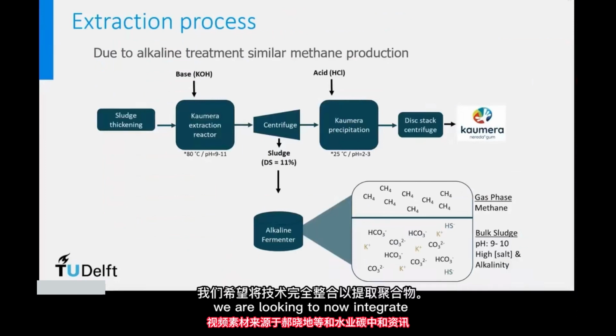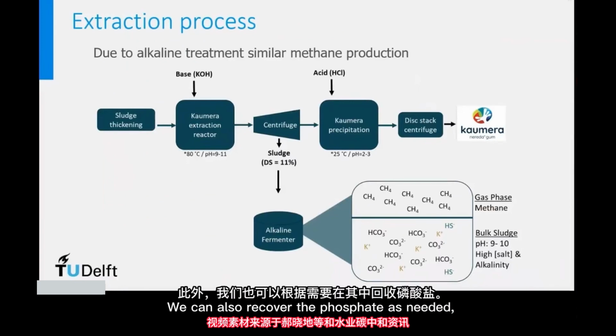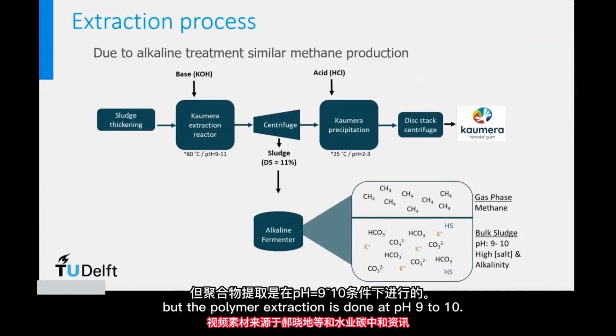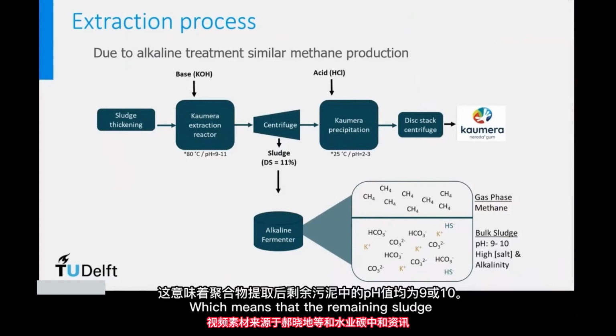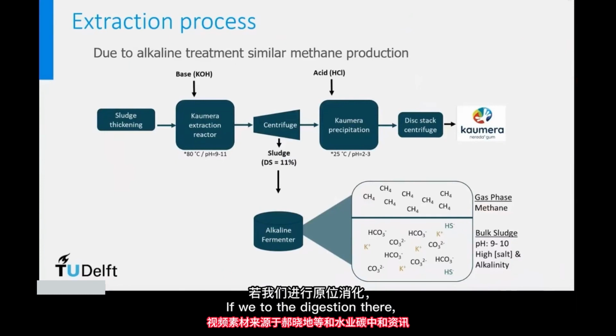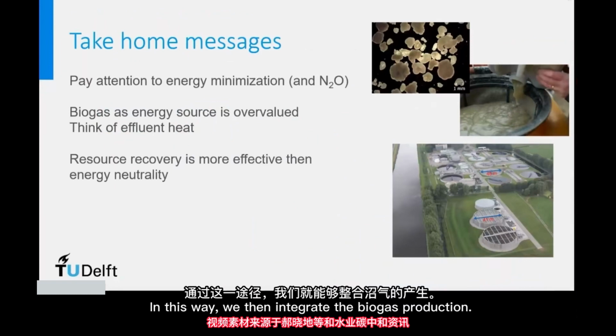So to finalize, we are looking to now integrate this fully, so that we can extract the polymers, we can also recover the phosphate as needed, but the polymer extraction is done at pH 9 to 10, which means that the remaining sludge after the polymer extraction, all that remaining organic carbon, is at pH 9 or 10. If we do the digestion there, then all the carbonate stays in the liquid and the gas will contain only methane gas. It is possible to do the sludge digestion at that pH, and then directly produce green gas and maybe even sequester the CO2, but that's a much longer way to go. And in this way, we then integrate the biogas production.